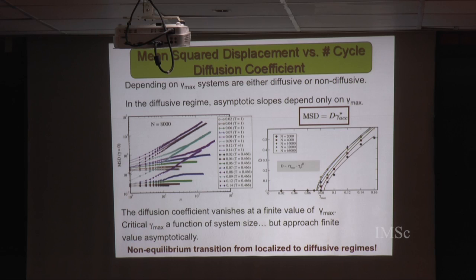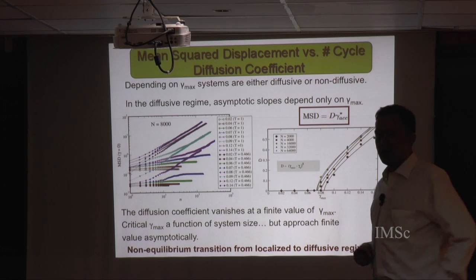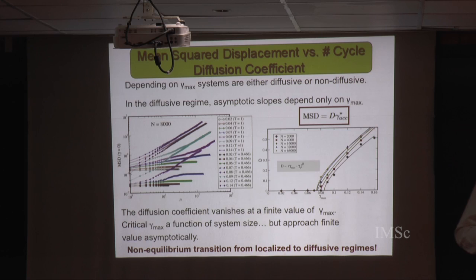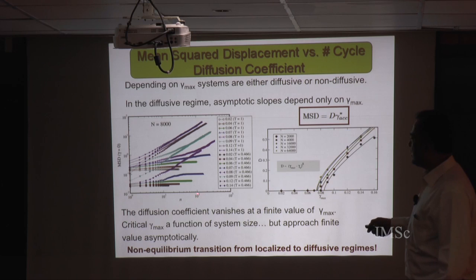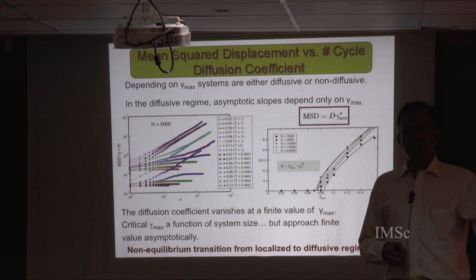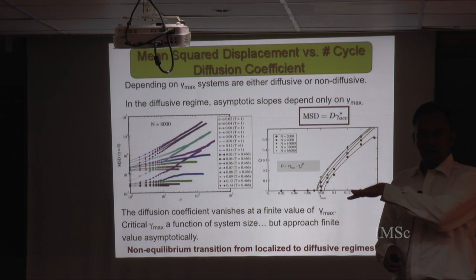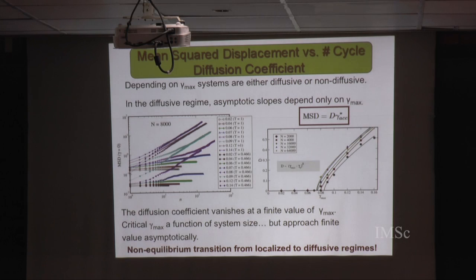So the other thing we can do is look at how much particles move in the process of this cyclic deformation. What I show here are mean squared displacements from the initial configuration, calculated as a function of the number of cycles. You find that for low amplitudes of deformation, if you look at these bottom curves, this mean squared displacement increases a little bit, but then eventually saturates. In other words, after a point, the system is not moving anymore.